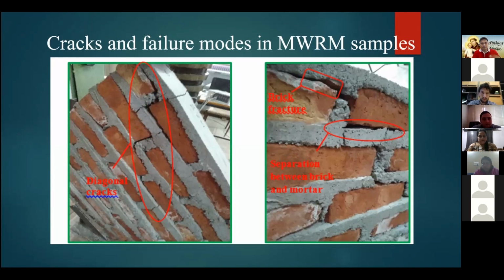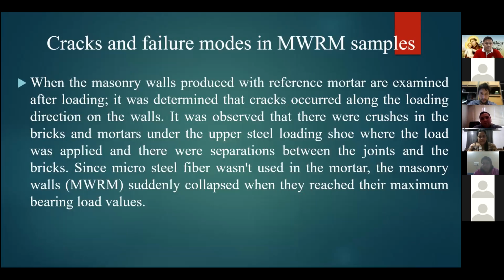Yes, of course. And diagonal cracks, brick fracture, and separation between brick and mortar. When the masonry walls produced with reference mortar were examined after loading, it was determined that cracks occurred along the loading direction on the walls. It was observed that there was crushing in the brick and mortar at the steel loading shoe where the load was applied, and there were separations between the joints and the bricks.